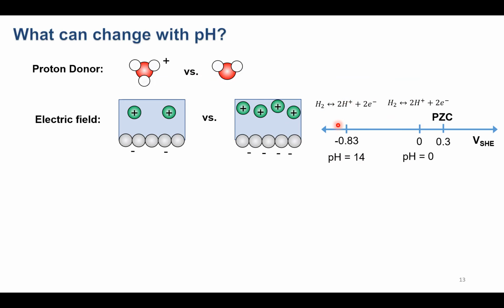And so that also causes a shift in the equilibrium potential for this reaction by minus 0.83 volts. So why is this important? Well, as far as we can tell, the potential of zero charge of an electrode surface is independent of pH. This potential of zero charge, or PZC, is the potential where the electric field across the surface is zero. And so sticking with platinum, the PZC of platinum is known to be somewhere around 0.3 volts on